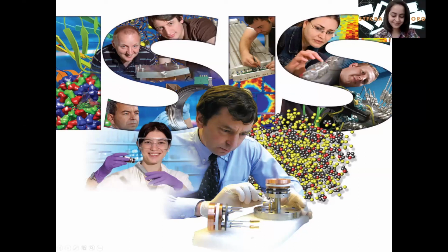Zori Akbari was asking about using neutron diffraction to detect phase evolution during battery operation. Yeah, so we definitely can do that. It depends on what battery systems you're looking at, and we will probably have to design a specific experiment for each different type of battery to maximize the amount of material that goes in the beam. But yes, crystallographic phase evolution we can do certainly very straightforwardly. If it's non-crystallographic, that poses a bit more of a problem, but it's not the end of the world. I'm sure we could work on something that will allow us to do that too.